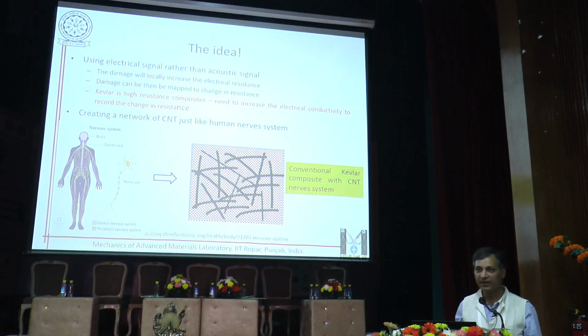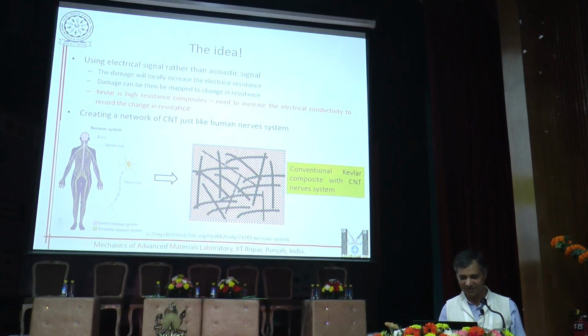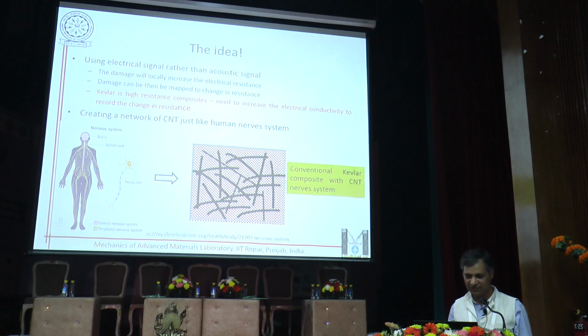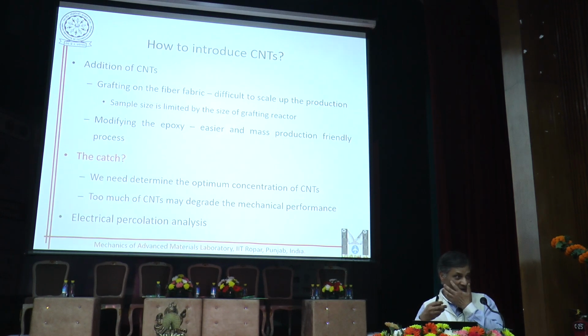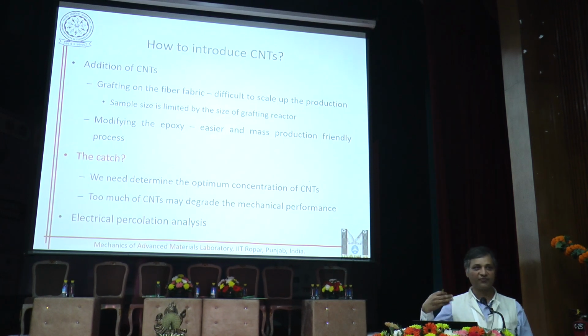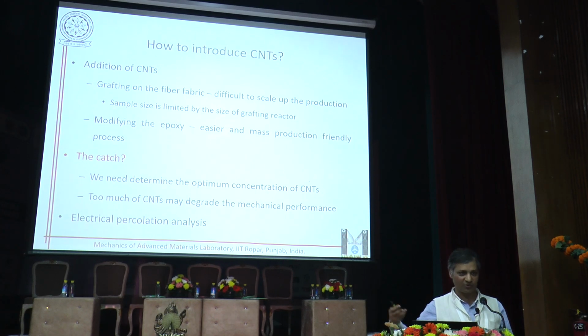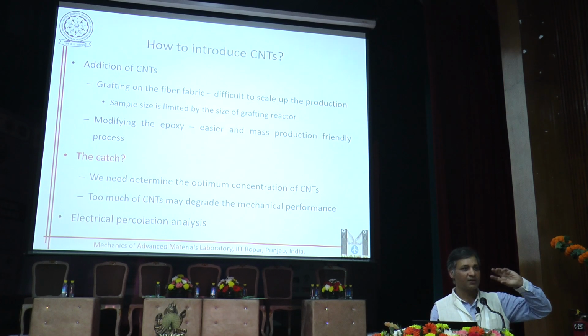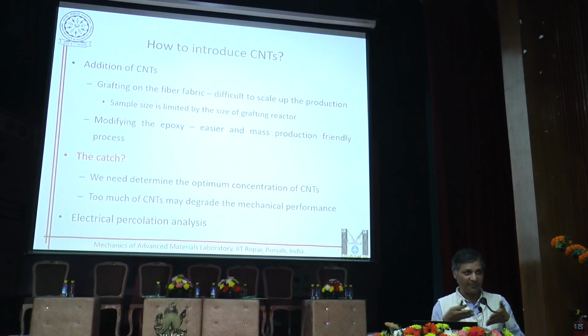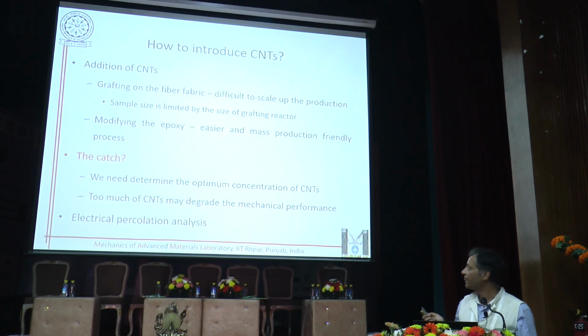Now the question is how do we add CNTs, because there are many approaches. The two approaches which we looked at: you can graft the CNTs on the fiber surface, like in one of the slides Professor Bond was saying, you have this porous electrode. You can also coat the fiber with the CNTs inside the CVD reactor. But the problem is that the size of the sample is limited by the size of the reactor. So you cannot really create a big sample. It is as big as the size of your reactor, and CVD is the mostly used technique. So we didn't prefer that in this.